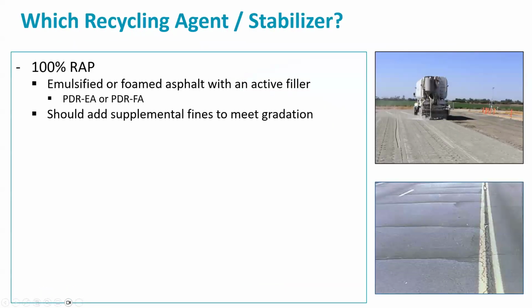Then comes the question of which recycling agent do we use, or stabilizer do we use? If we're processing 100% RAP, then we stick with asphalt treatments. We either use emulsified asphalt or we use foamed asphalt. They're going to give you essentially the same result at the end of the day. So we can't say one is better than the other. There are instances when it's probably better for the contractor to use an emulsion, and there are going to be some instances where foam is better.